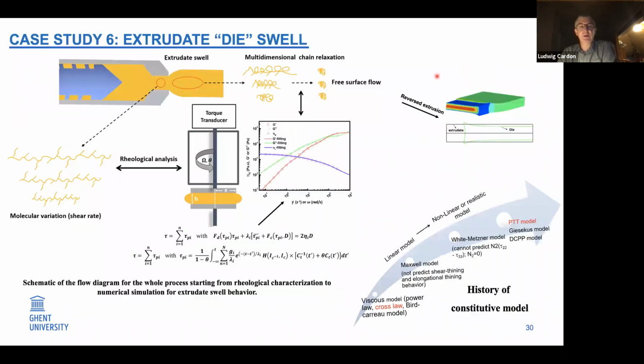And by mimicking that, going back to the previous slide, we look inside the output pressure. We try to have a uniform flow. When there is a variation, we can control the speed or the flow behavior, the stability of the extruder. But on the other hand, what's also illustrated here, taking in mind the aging, we also look inside the molecular variations, the shear effects, and finally trying to find out what happens with the different steps of your polymer. So depending on the molecular variations inside your material, and the type of blend, could be a polypropylene with a low or a high molecular mass, depending on that we have a different die swell.